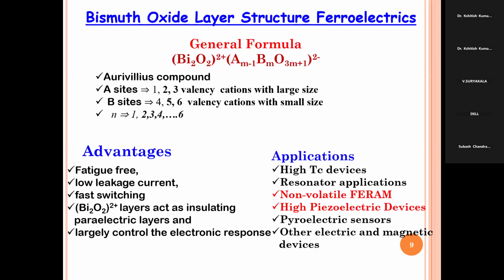And fast switching. And why have we taken this type of material? Because this is nothing but the perovskite material I have already told you about, ABO3 type material, but in the ABO3 the bismuth layer is present, and that bismuth oxide layer acts as an insulating paraelectric layer. For that reason it is fatigue free, and it sustains up to 10 to the power 12 cycles. And for these advantages, the materials are used for high transition temperature devices, resonator applications, non-volatile ferroelectric random access memory, high piezoelectric devices, pyroelectric sensors, and other electric and magnetic devices.